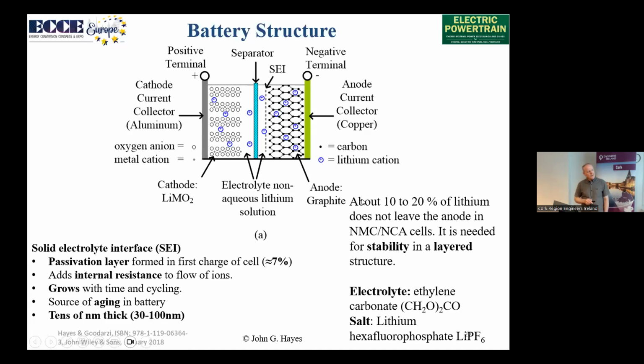So I showed this as the cathode, a nickel type cathode with these layers. So the lithium ions are going to be stored, intercalated, in these layers. We need to retain about 10 to 20% of the lithium within the cathode in order to basically hold up the structure. If I fully discharge the pack, move all the lithium out of the cathode for this type of cell, the cell will die. So we always keep, probably in a modern cell, maybe about 10% back, but it used to be a higher number in earlier cells.